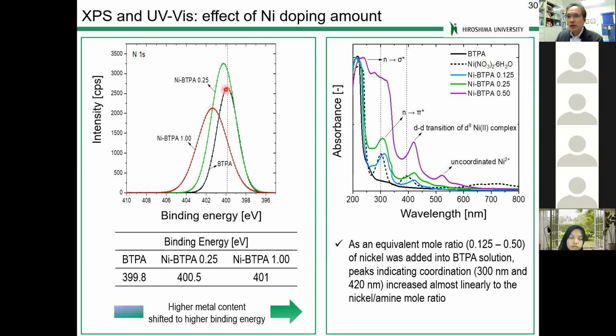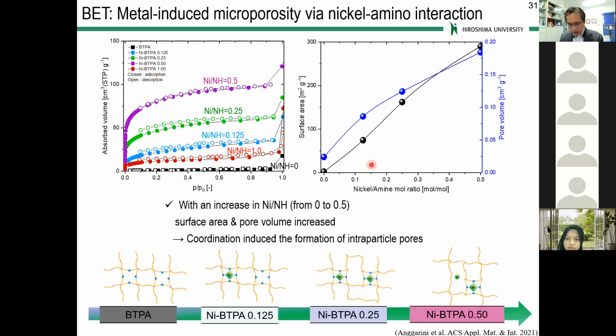This is the case of the pure BTPA. And then after doping nickel, a shift was observed. The UV spectra indicate this is the case of the pure BTPA, and this is nickel nitrate. We observed new peaks, right? So this suggests coordination occurs by doping with nickel nitrate. Now this is the case of the nickel amount effect. The nickel amount was increased: 0.125, 0.25, 0.50. Surface area increased almost linearly with the doping amount. This also confirms the coordination may induce the formation of intraparticle pores.